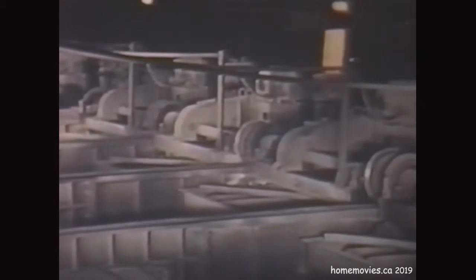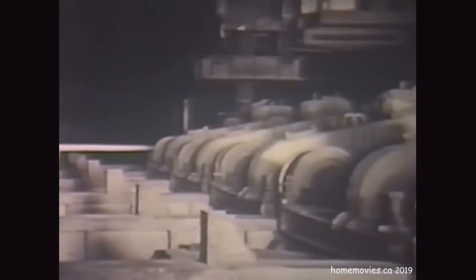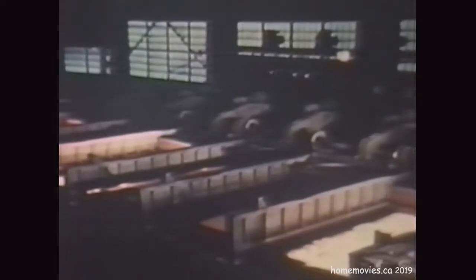There's the next stop for the new steel. Deep soaking pits where the ingots are steeped in heat until they're uniformly hot right to the core. Strong, almost human mechanical fingers snatch at the ingots lying loose in their molds and hoist them into the air for the trip to the soaking pits. With not even a momentary pause, the fingers swoop down with their weighty burden. Electrically operated covers slide back from the long battery of pits, revealing the heat and flame-filled caverns underneath.